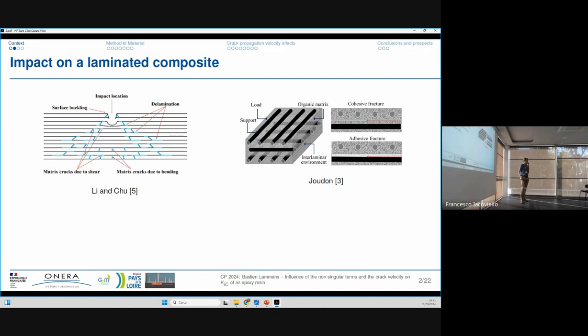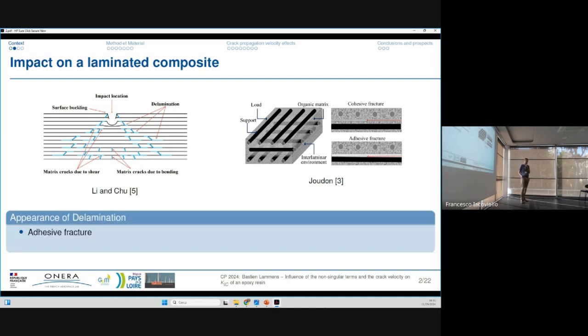When we speak about delamination, there are two types of fracture: adhesive fracture, where the crack propagates at the interface between the matrix and the fiber, but there is also cohesive fracture, when the crack propagates only in the matrix, in the resin. So in my work, we have only focused on cohesive fracture.